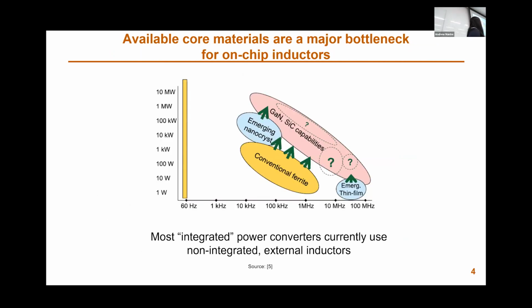And in order to do that, as Alyssa said, in order to make these inductors as small on the chip scale, we have to operate power converters at really high frequencies. And for chip scales, that typically means above a few megahertz, like 10 megahertz and above. And the main bottleneck for magnetic components at these high frequencies are the core materials available now for power. Basically in power, we always typically use ferrites, even in lower frequency stuff. And all of the conventional ferrites have too much core loss, so we can't use them. So my research is basically what's a better core material for this particular application.